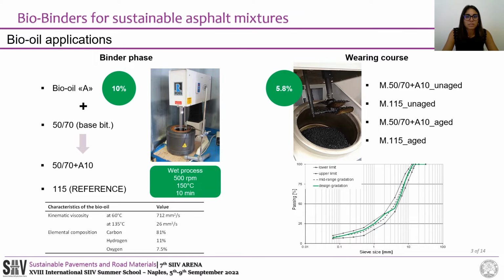The blend was obtained in laboratory through the use of a high shear stirring mixer, setting the speed, the temperature and the timing. From previous studies and in accordance with what is found in literature, it emerged that the bio-oil addition causes a consistency reduction. For this reason, a plain bitumen characterized by a similar consistency, 115 penetration grade, was selected